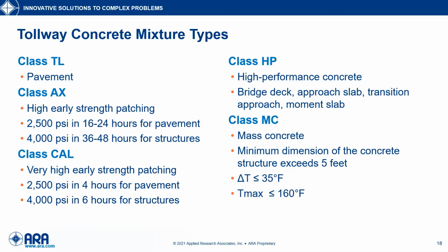So Class TL is the mixture used for pavements. Class AX is a Portland cement-based high-early strength patching mix that can be used in both pavements and structures. 2,500 PSI is our opening strength for pavement patching, and the AX mixtures can usually achieve that in about 16 hours. Class CAL is relatively a new mixture type. It's used for very high early strength patching and uses calcium aluminate cements along with a latex admixture. The Class CAL mixture can easily achieve the 2,500 PSI opening strength in about 4 hours.